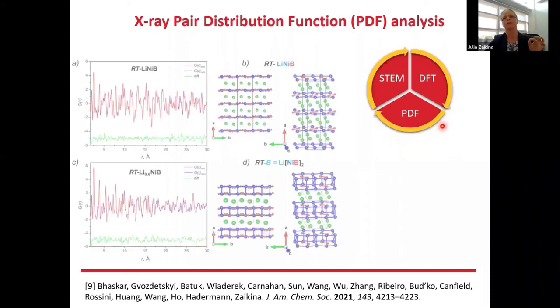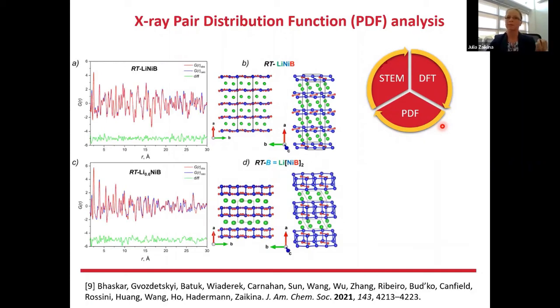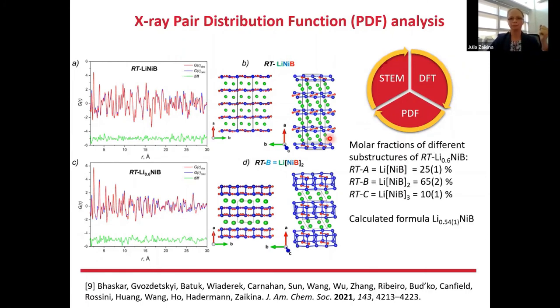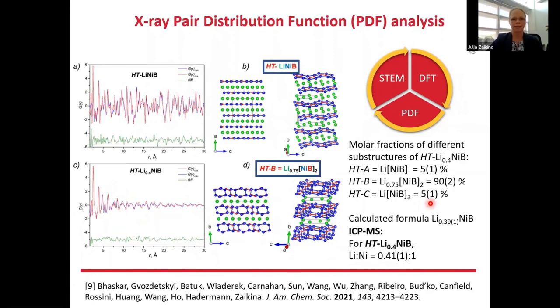Because we use X-ray PDF, we can locate the positions of the heavy atoms, nickel in this case. So we use the DFT again to optimize the positions of the light atoms such as lithium and boron. And so using those 3 methods allows us to determine the molar fractions of each substructure, and the calculated formula agrees very well with the compositional analysis performed by ICP mass spec. So we get a very good fit of the data by using all 3 models simultaneously, and we now can also determine the interatomic distances and precise location of atoms within each model. And similar for the high temperature polymorph, we use the same approach.